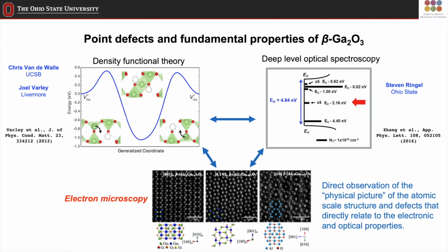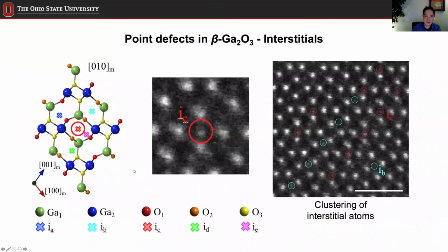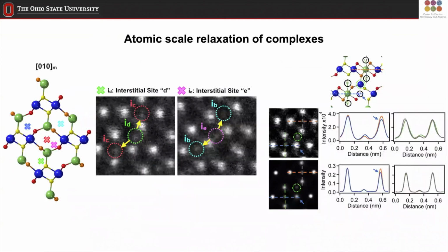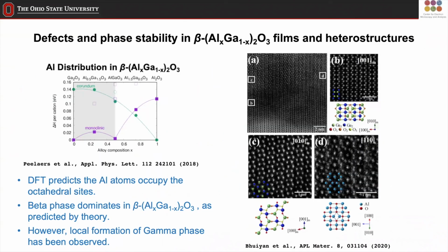For the mixture, say gallium oxide doped with aluminum, the thin film case, you talked also about the importance of the thickness for the formation. So why does thickness matter? Is that because of the lattice mismatch between substrate and film? Up to a certain thickness, then the strain will change in terms of the intensity or something else. Yeah, that's an important point.